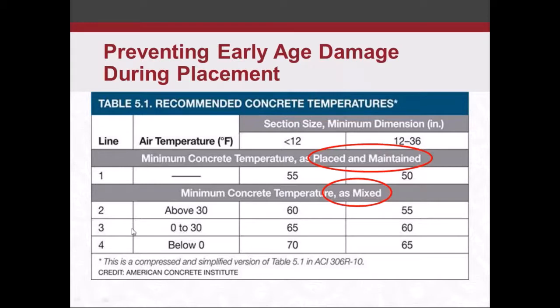The bottom part of this table has mixed temperatures based on ambient temperatures. So above 30 degrees, minimum mixed temperature is 60 degrees. Larger, thicker placements, we can go down to 55 degrees. 0 to 30 degrees, we're at 65 degrees. Below 0, we're at 70 degrees. So that's the concrete mix, as it's mixed. We want to make sure that we have that 60, 65, or 70 degrees for our concrete.